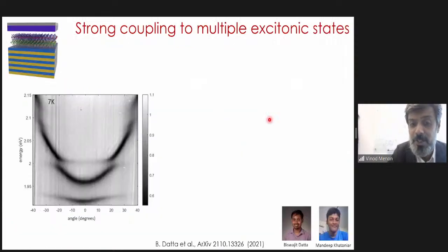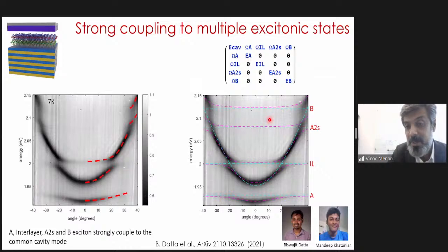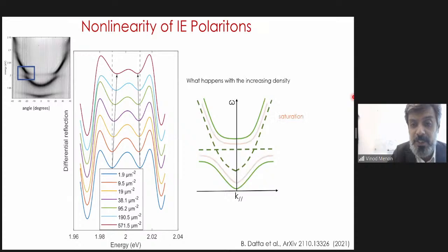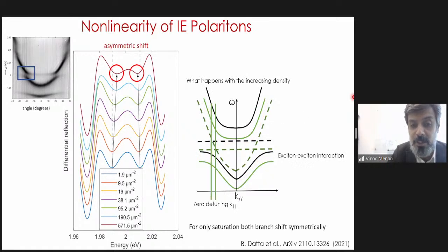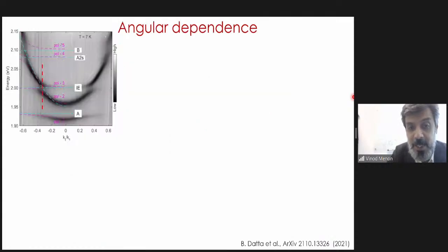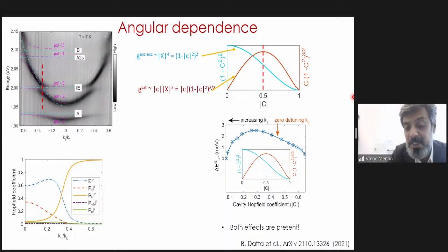So great. So we now know that you can get excitons with a permanent dipole moment. We actually then showed that you can get strong coupling and all of that. But really what we wanted to do was to prove that these interlayer excitons actually have a higher nonlinearity than my standard A excitons. This is work led by my postdoc Vishwajit and my then graduate student Mandeep. What they showed was, if you look at the shift of these branches, there is a contribution from both the phase space filling effect and the effect due to the exciton-exciton exchange interactions and the dipolar interactions.